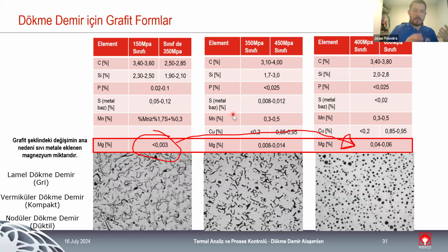Another element that is really important when we are dealing with different types of cast iron is sulfur. The sulfur in the base metal is really important because normally it could be higher when we are producing gray cast iron, because sulfur does not impact the shape of the graphite a lot. Sulfur basically blocks the growth of the graphite. But when we are dealing with nodular, normally we want less sulfur, so we need to be extra careful with the amount of sulfur, again because sulfur is blocking the growth of the graphite nodule. And the magnesium that we add during treatment is basically to catch the sulfur that is in the melt. So if you have a lot of sulfur, we need to increase the magnesium treatment, so we need to waste more magnesium during treatment.